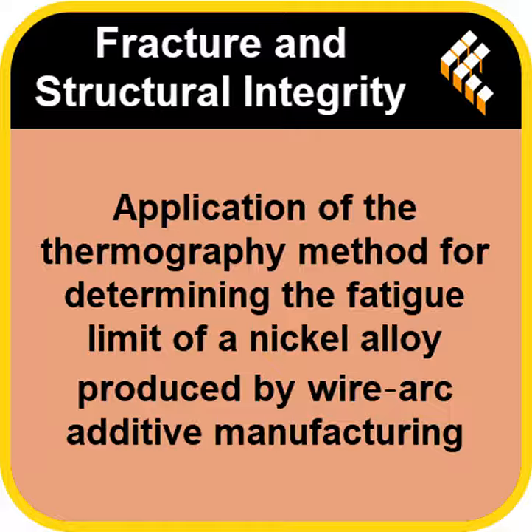They needed to cycle the material really, really fast to generate enough heat in a short time. So they used a high-frequency resonant testing machine. It was basically pulling and relaxing the material samples at 125 hertz. 125 times a second. Every second. Yeah. It simulates the kind of constant vibration you'd find in a high-speed engine.